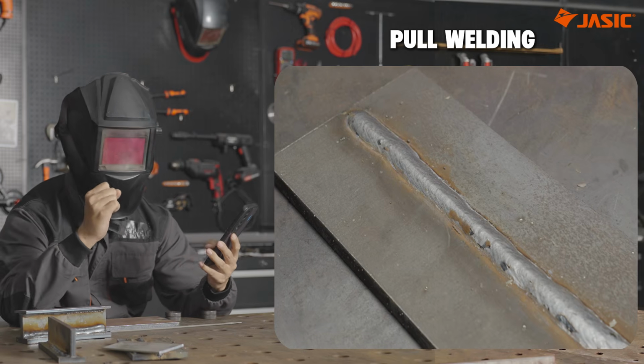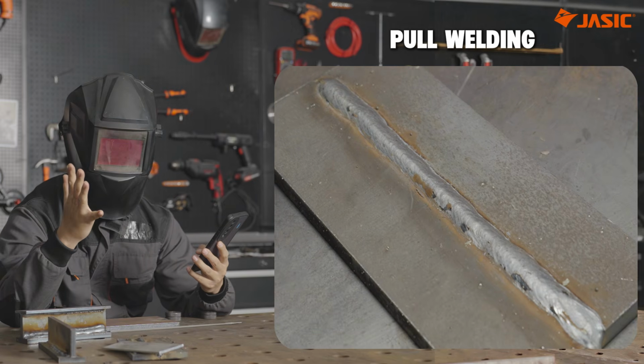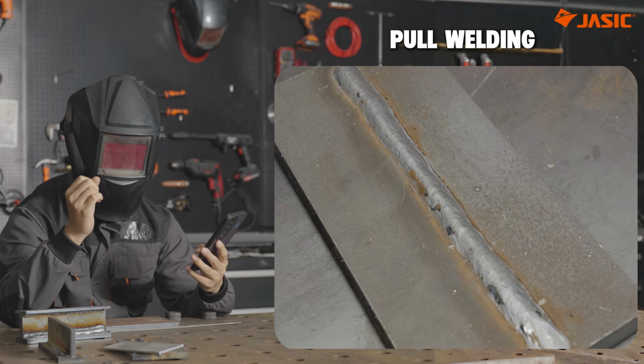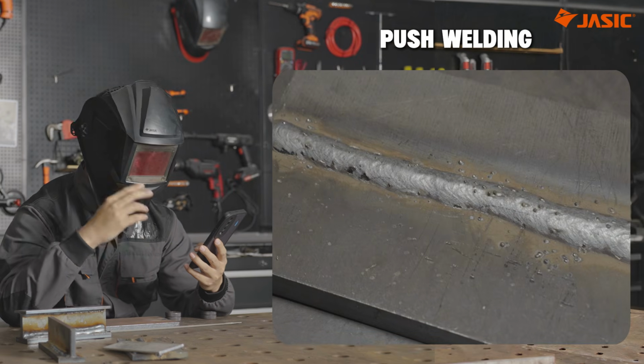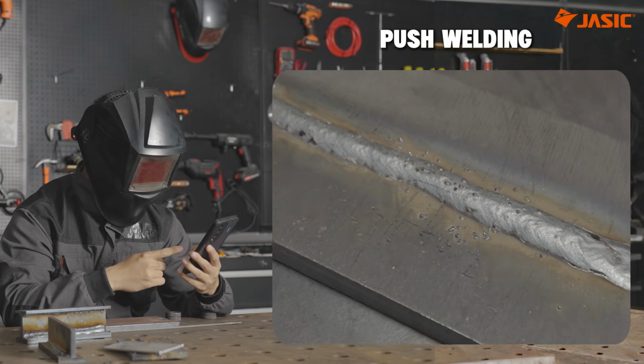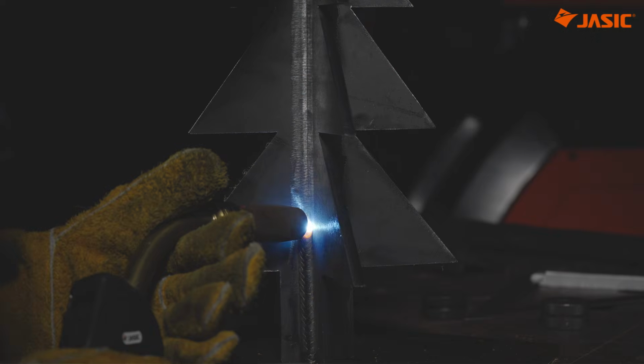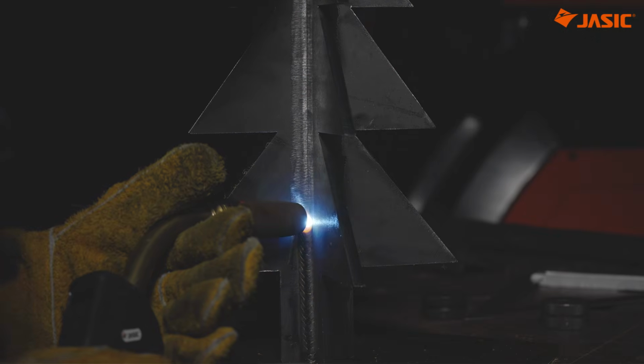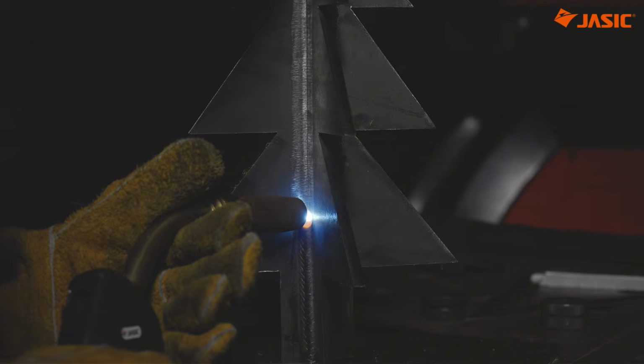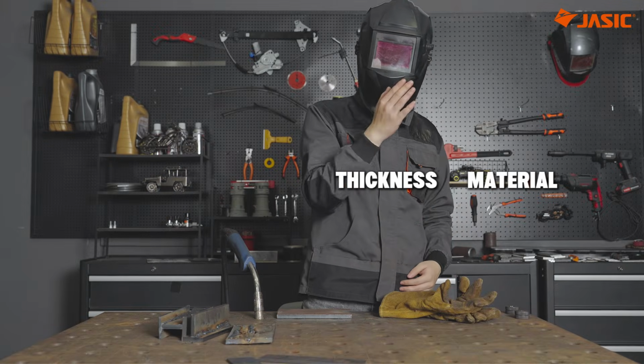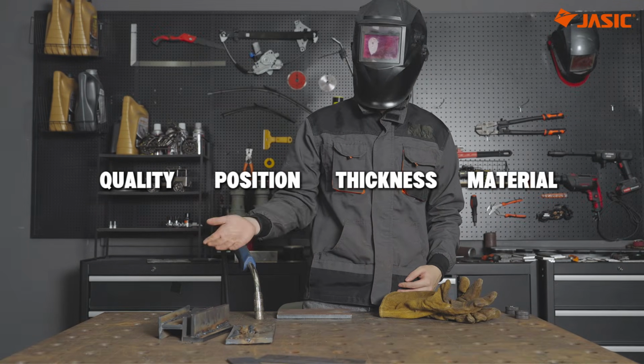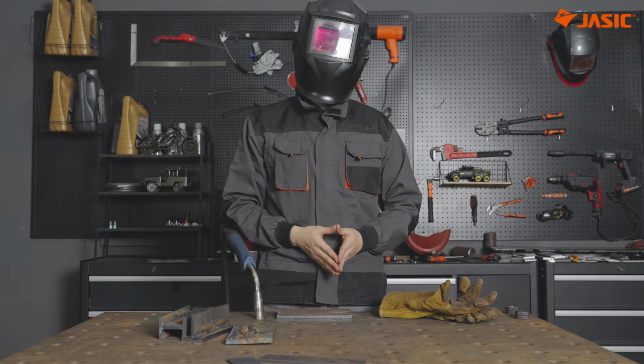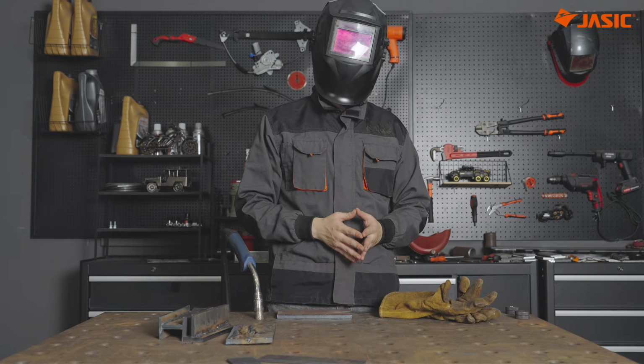Pull welding offers deeper penetration and better root fusion, making it the preferred choice for thicker materials and full penetration. Push welding provides better visibility, stronger gas shielding, and a flatter looking bead. In real-world fabrication, you'll rarely use only one technique. The best welders know when to push and when to pull based on the material thickness, welding position, and quality requirements. Mastering both techniques is an important step toward becoming a skilled MIG welder.